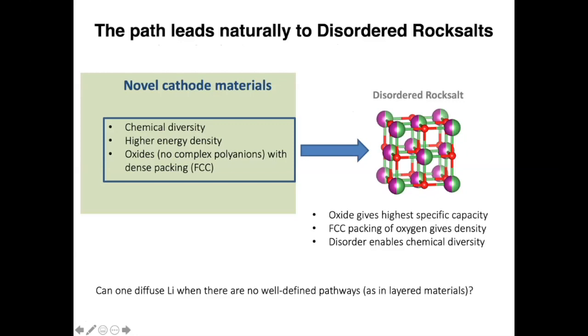So first of all, the chemical diversity. If you don't care about having a specific ordering of the cations, then you can use all kinds of chemistries, because some of them will disorder, some of them will give you other ordering. So if we can make a disordered rock salt work, we can actually use a much more diverse set of elements. Rock salts, of course, have the FCC packing of oxygen, and that will give you the high crystal density, and therefore, if you have high specific capacity, also the high specific energy. So the big issue with disordered cation materials is whether you can make lithium diffuse in them.